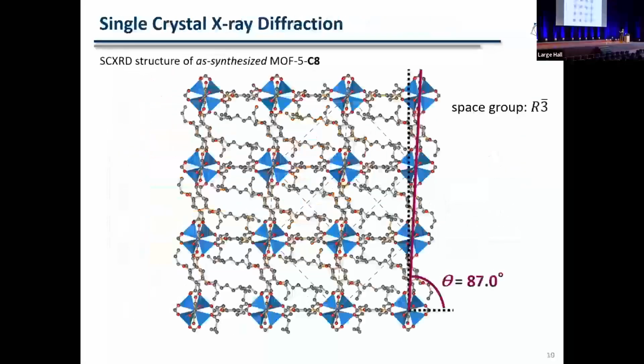And when we look at the crystal structure, so we get beautiful crystals of this. You get the crystal structure of this material decorated with these long alkoxy chains. Interestingly, these chains are ordered in the material. So it's quite packed already. There's some void space left, but it's quite packed. So everything orders. The linkers order. And you see there's a slight deviation from the 90-degree angle. So it's no more cubic, it's a rhombohedral structure. So far, so good.